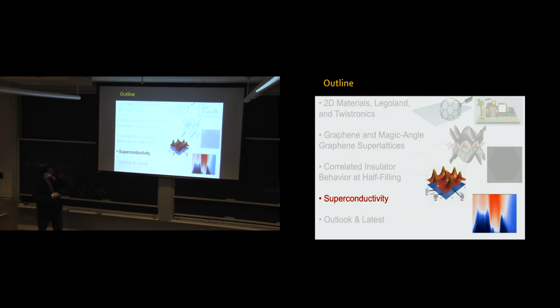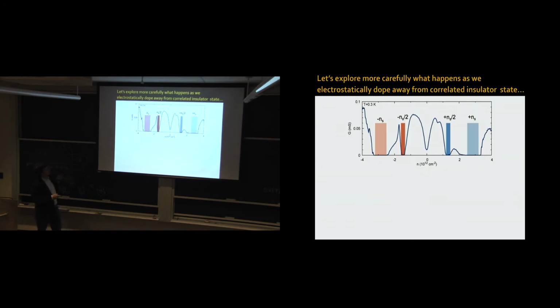Now let me show you about our superconductivity. So we had this data, conductivity versus density. But these data are in devices which are measured in a two-terminal geometry. What does it mean? It means we have a source and a drain contact, just two contacts. This is a geometry which is very convenient if you want to measure an insulator, because if something is going to have infinite resistance, you do not care that you're adding a little bit of extra resistance with your contacts. However, if you want to see if something conducts very well, you do care if there's some parasitic series resistance, so you want to change the type of device geometry.